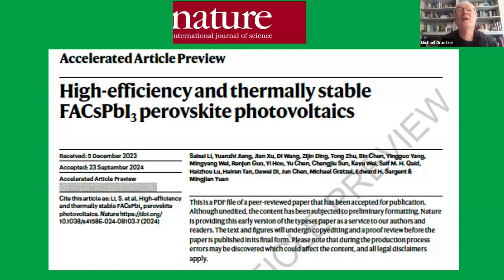perovskite cells. However, there was a drawback with the cesium when you use those mixtures. I should mention that the films are made from solution processing. You have the precursors in solution, and then you spin coat the ink on the conductive support. Then you add an anti-solvent or remove the solvent, and precipitation of the perovskite happens. However, what happens with these formulations is that the cesium precipitates much faster than the formamidinium. So you get an inhomogeneous distribution of the cesium across the film. And so that needs to be controlled.